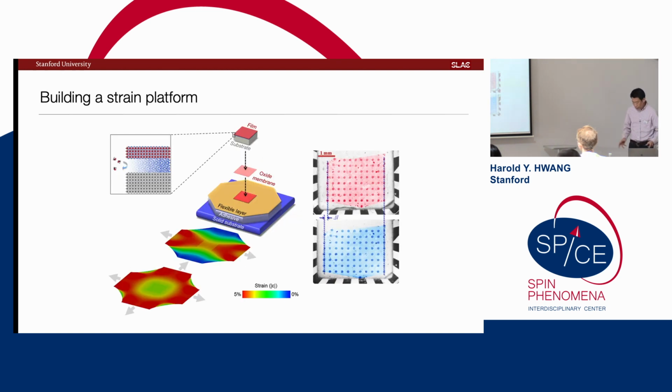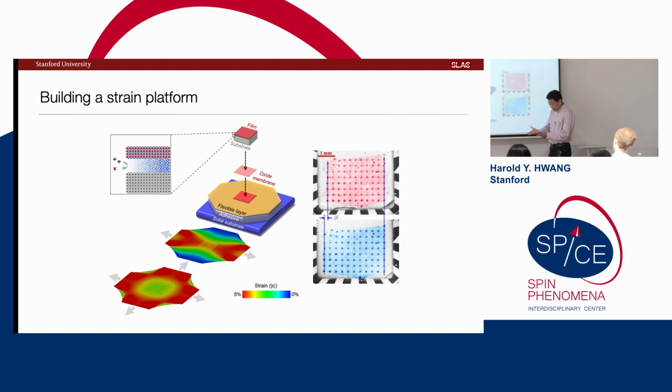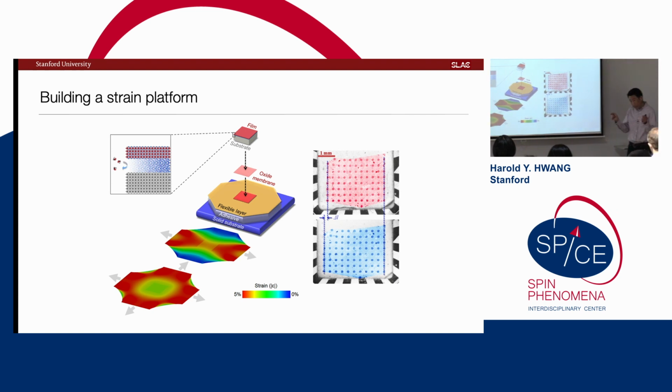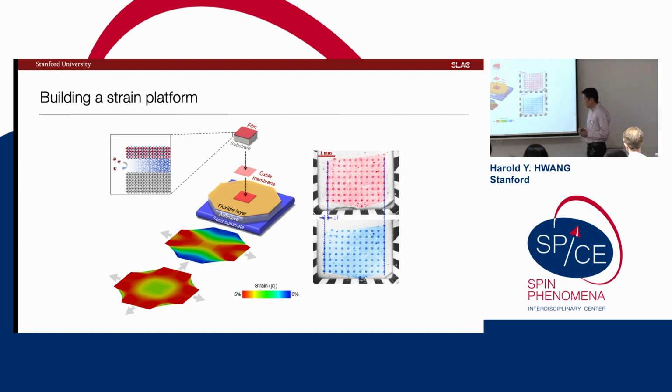So I'll just give you a few examples of what can be done. Again, a lot of this is just trying to find different experimental approaches. What we found is that the oxides can be functionalized and stick really well on things like polyimide or Kapton, so their interface adhesion is very strong. I won't go into the details, but this seems to be, in retrospect, a very useful way to strain very aggressively without starting and propagating cracks. Here's an example of a membrane that we've stretched pretty aggressively in one direction.